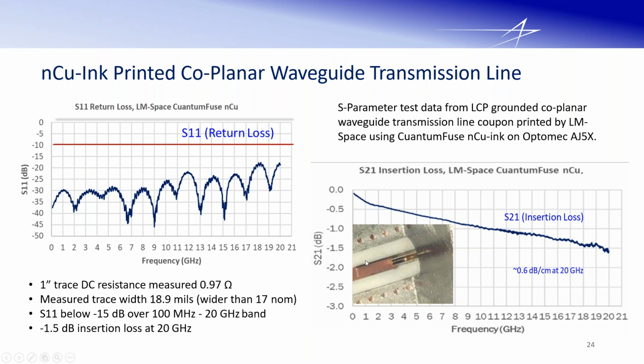So here you have the nano copper printed, the DC resistance for that 1-inch line. The coupon is you're basically printing a 1-inch line, and it was 0.97 ohms. So a little higher than foil copper. If this was foil copper, it would be less than 0.1 ohms. So it was a higher resistance than just bulk copper. The trace width was a little bit wider.